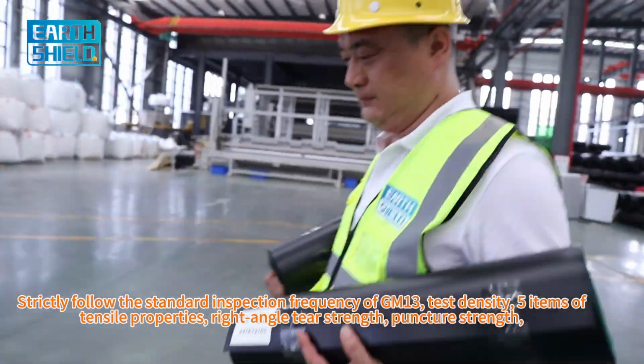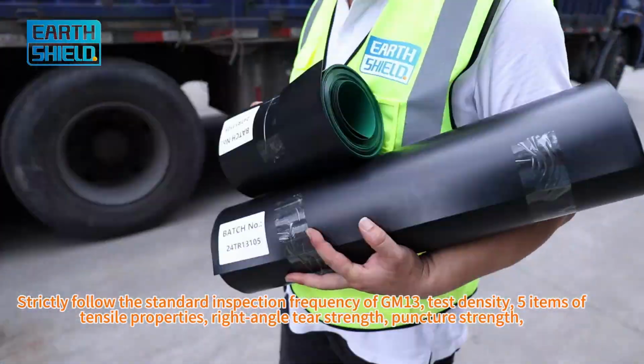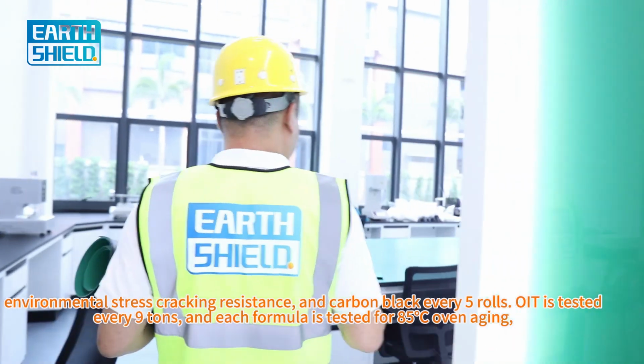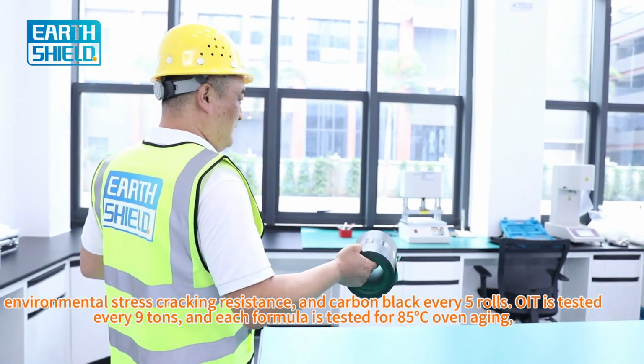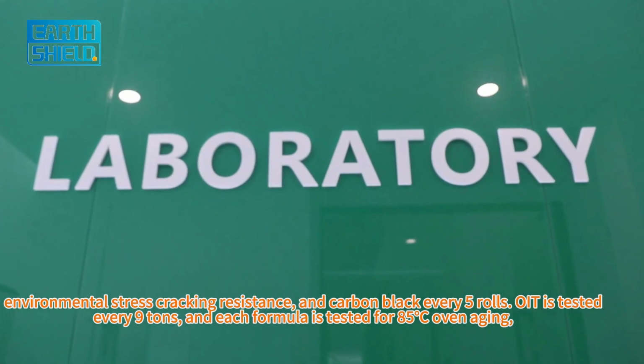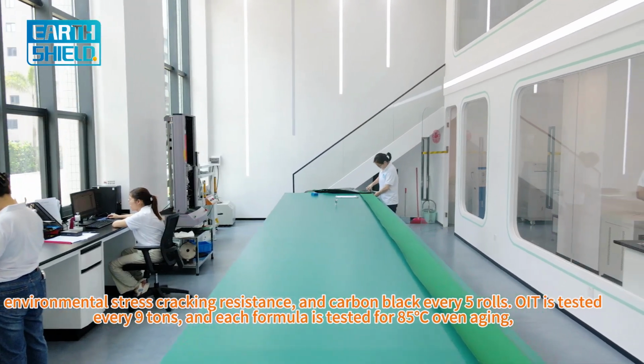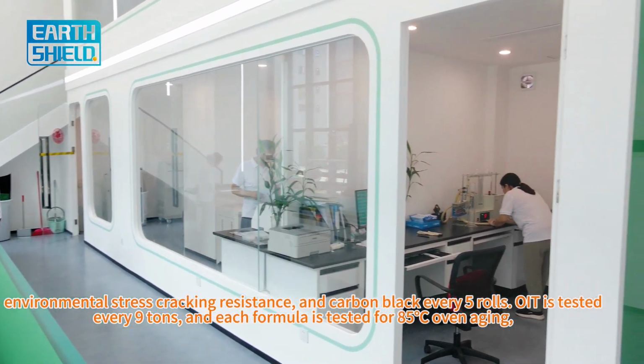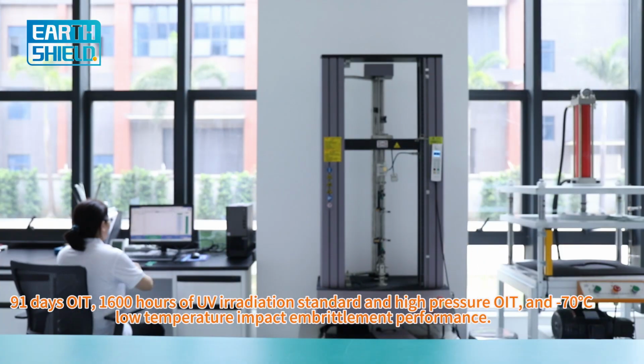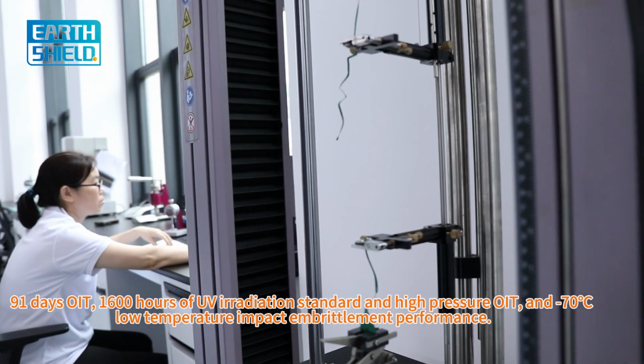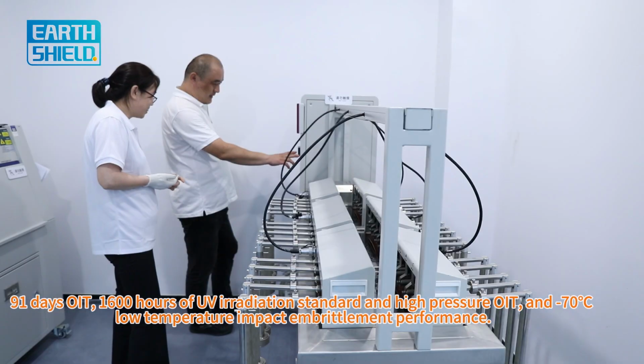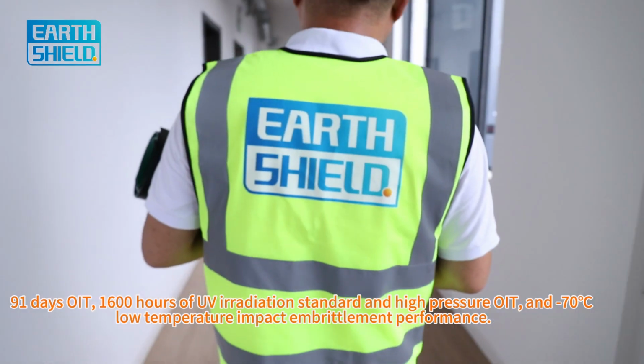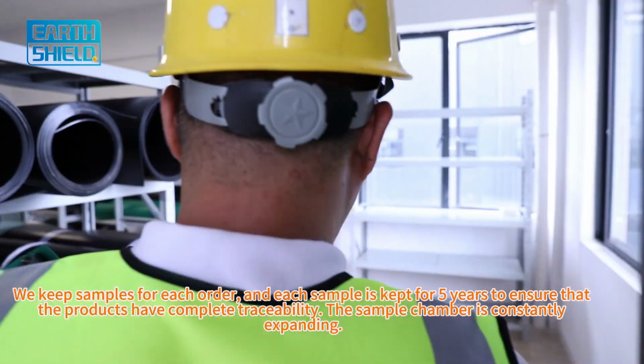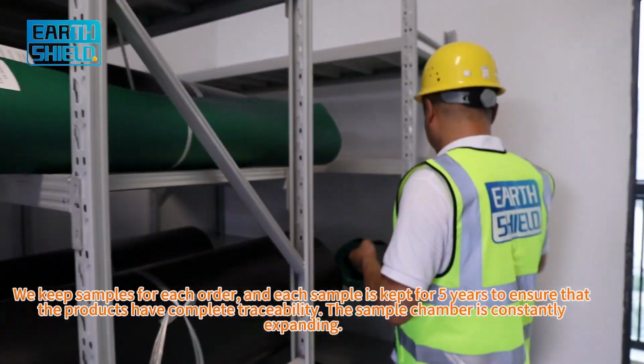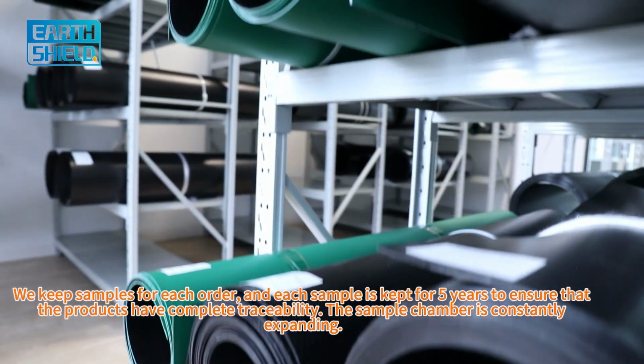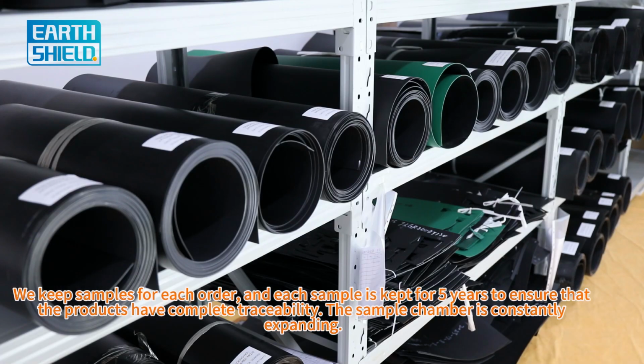Test density, 5 items of tensile properties, right angle tear strength, puncture strength, environmental stress cracking resistance, and carbon black every 5 rolls. OIT is tested every 9 tons, and each formula is tested for 85 degrees centigrade oven aging, 91 days OIT, 1600 hours of UV irradiation standard and high pressure OIT, and minus 70 degrees centigrade low temperature impact embrittlement performance. We keep samples for each order, and each sample is kept for 5 years to ensure that the products have complete traceability. The sample chamber is constantly expanding.